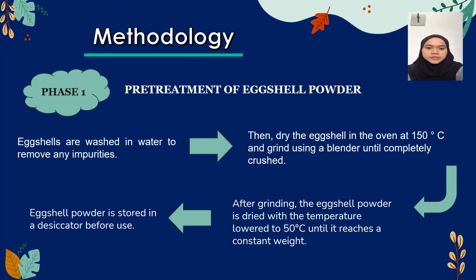Okay, on methodology, phase 1 is preparation of eggshell powder. First, wash the eggshell in water to remove any impurities. Then, dry the eggshell in the oven at 150 Celsius and grind using a blender until completely crushed. Third, after grinding, the eggshell powder is dried with the temperature lowered to 50 until it reaches a constant weight. Lastly, eggshell powder is stored in a desiccator before use.